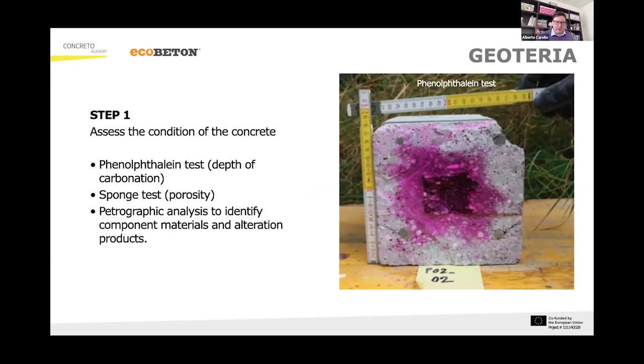preliminary test. We start with the phenolphthalein test, that is this purple stuff that you see on the sample, and this measures the depth of carbonation. Carbonation, I told you before, is one of the biggest enemies of rebar, steel rebar in concrete. And it is responsible for starting a chain that leads the concrete to destroy, basically, because the rust is going to grow the rebar and then make pressure on the surface and then act what we call spalling of the concrete, okay?